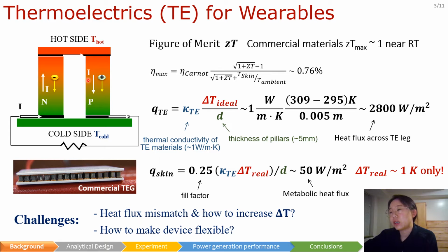On the other hand, thermoelectric generators that convert a temperature difference into electrical energy can provide power to wearable devices and other IoT devices. The dimensionless figure of merit ZT has been widely used to quantify how good the thermoelectric materials are, as we can see from the formula of eta max, the maximum efficiency of heat conversion into electricity by a thermoelectric device. The current commercial materials usually have a maximum ZT around 1 near room temperature.